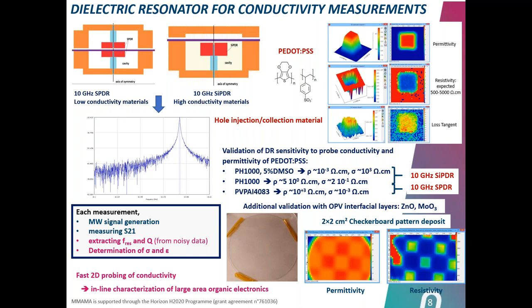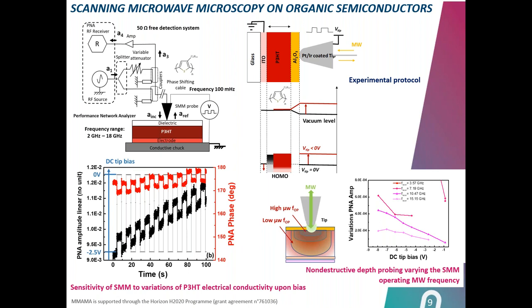That is the ability, by incorporating a two-dimensional scanner on the dielectric resonator, to make a mapping of the electrical properties when you have, for instance, in this case, a checkerboard of PEDOT:PSS deposited on quartz. So you can see, you can map electrically this checkerboard. And the spatial resolution was shown to be on the millimeter scale, which is quite powerful for evaluating large-scale organic photovoltaics. The last example was carried out at the nanoscale, where using a scanning microwave microscope, it was possible